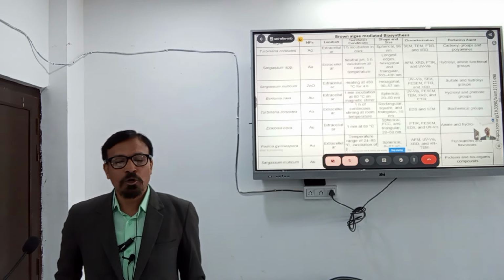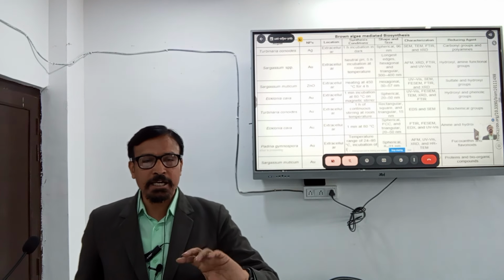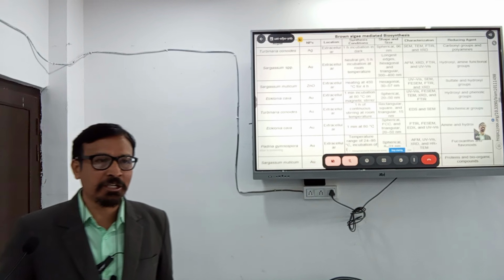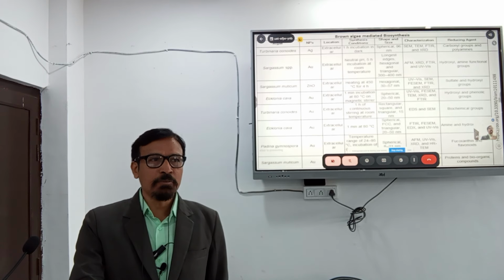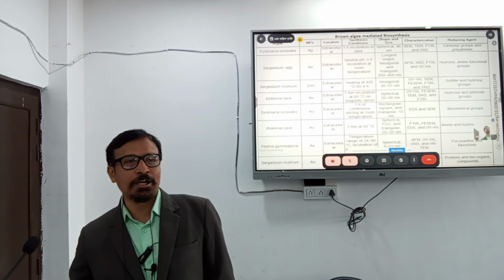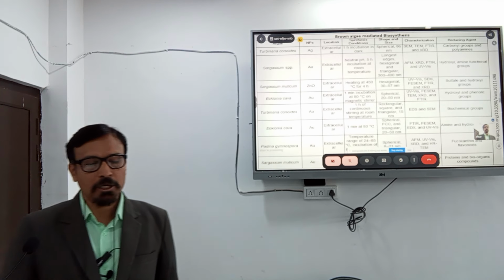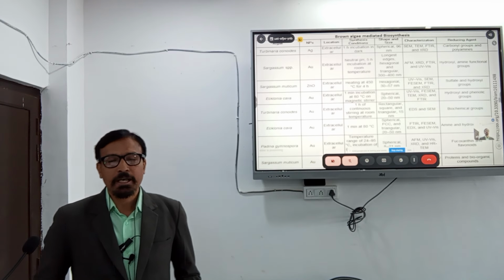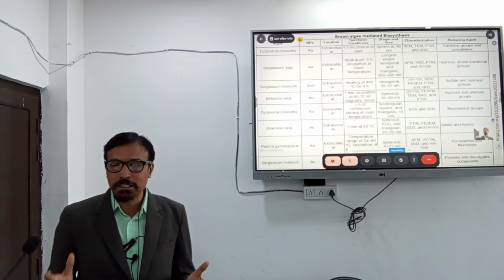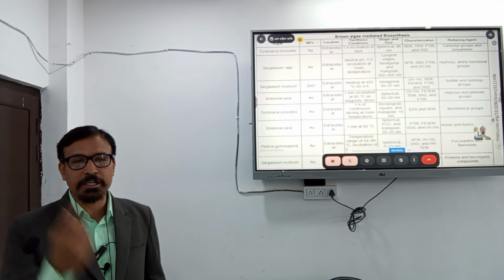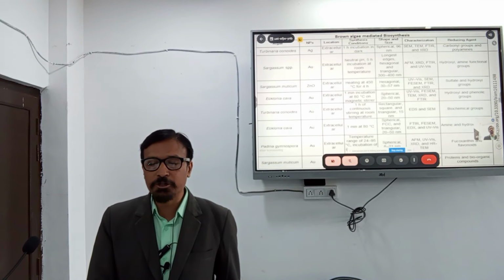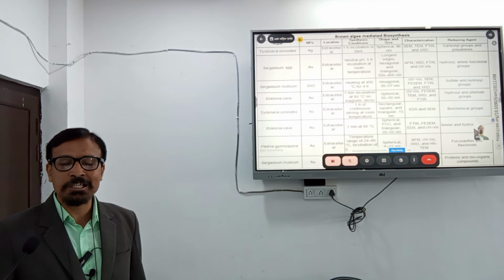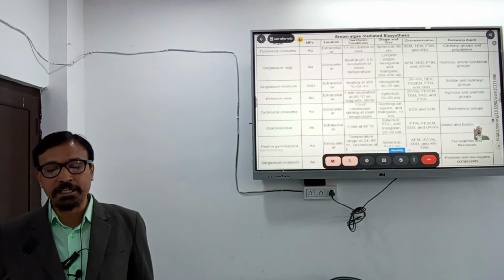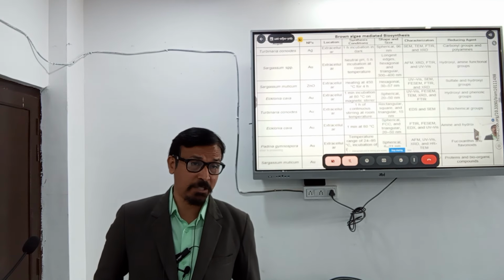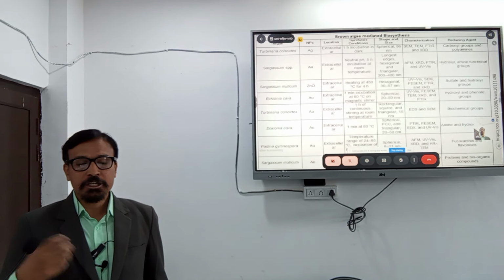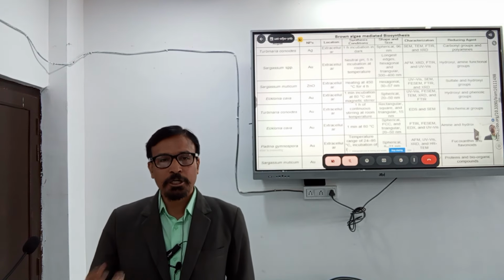Next is Turbinaria conoides also, which I have already mentioned earlier, but this time we can produce gold nanoparticles instead of silver nanoparticles. So Turbinaria conoides, extracellular location, and the synthesis requires 1 hour of continuous stirring at room temperature. Room temperature is sufficient, and the characterization of these gold nanoparticles can be done by EDS, that is energy dispersive X-ray spectroscopy, and SEM. And these are the biochemical groups, the reducing agents.